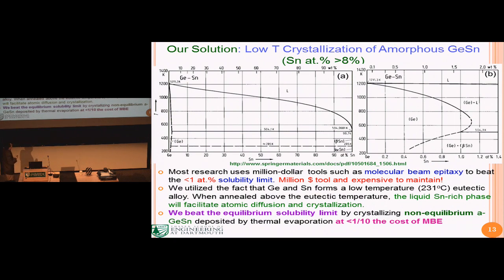If you look at the phase diagram of germanium tin, there are two ways to look at it. One is a frustrating way. The other is a promising way. So I'll talk about the frustrating way first. Take the phase diagram. You do what my students would do in 24. Okay, room temperature, 300 K. I find the intersecting point over here, and I read how much tin can I dissolve in germanium without segregation. Unfortunately, that's only about 0.5%. Compared to 8%, this is a huge gap. If you want to increase this to 8%, that's an extraordinary effort.